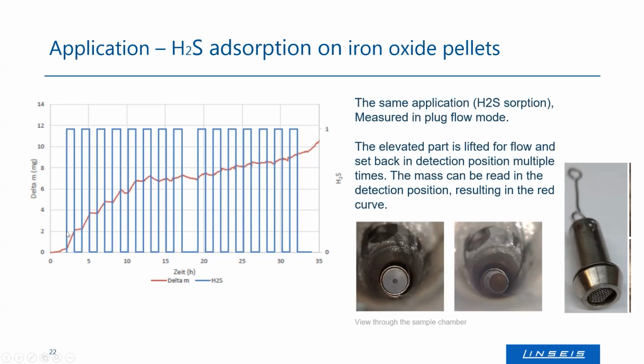So you have cycles. The blue cycles are the H2S gas flow cycles. So you put it on the bottom, you activate the gas flow, you disable the gas flow, you lift it and get a weight information. Then you put it down again, you increase the gas flow, you lower the gas flow, you lift it, and so on. Out of these cycles, you get data points each time you lift up the complete thing, and each time you lift it up, you get values for your weight change.